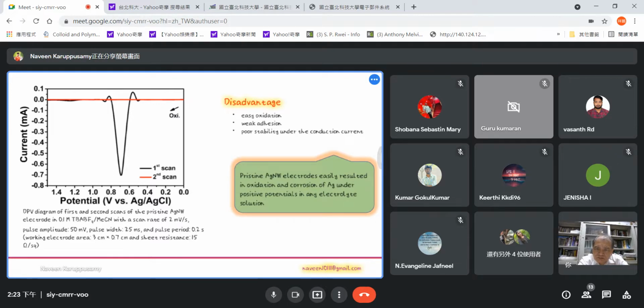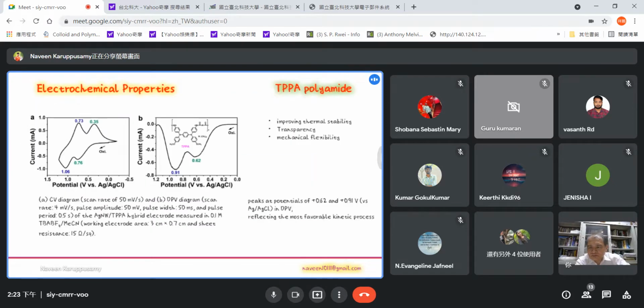That is the reason for the research group to fabricate a passive layer over the silver nanowire. This electrochemical property. After the fabrication of the triphenylamine polyamide passive layer over the silver nanowire, in this CV performance we can clearly see two oxidation peaks, observed at 0.76 and 1.06 potential. Next, the DPV performance also shows two oxidation peaks, one at 0.62 and another at 0.91, which clearly shows the improved thermal stability, transparency, and mechanical